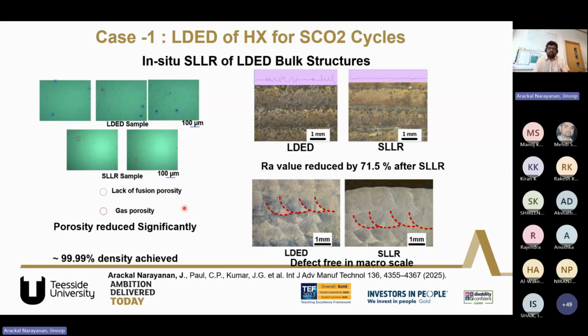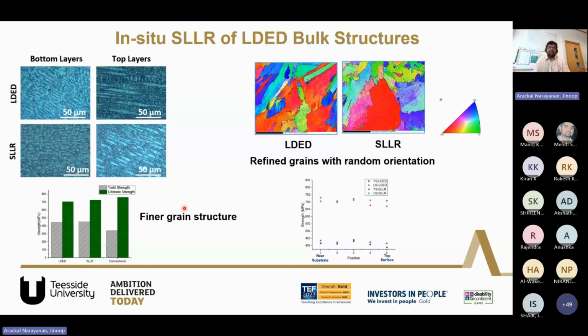We could refine the grain structure to some extent, and we could reduce even the grain orientation or the grain growth orientations.